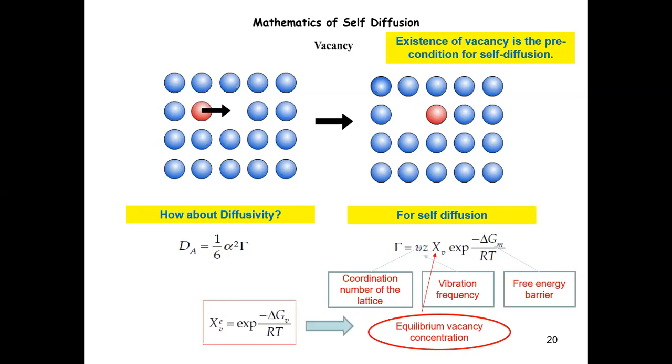Okay, so basically why vacancies are equilibrium defects is that they're favored at high temperature because they increase the entropy of the system, and through that they stabilize the system. This is also a mechanism for why melting is inevitably related to vacancy concentration, right?